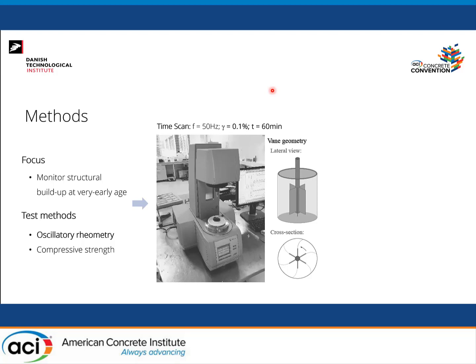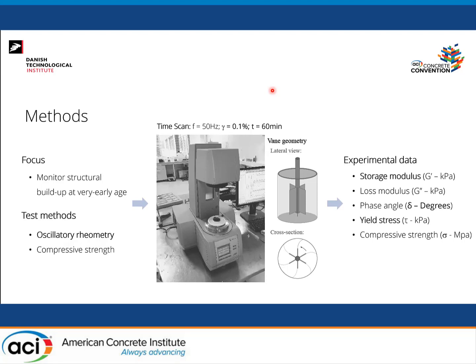So this test was mapping the evolution of, let's say, altogether structural buildup in simple terms over the course of 60 minutes. And then we get information like the evolution of storage modulus, loss modulus, phase angle, as I mentioned. The yield stress can be estimated, and I'm very happy to see Reza's presentation. The first presenter was showing some of the relationships between how you could get storage modulus with E modulus and then some indications of yield stress.